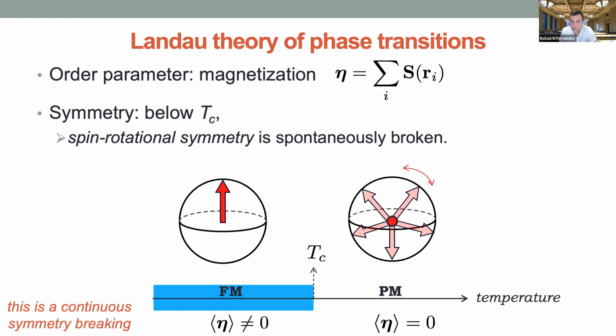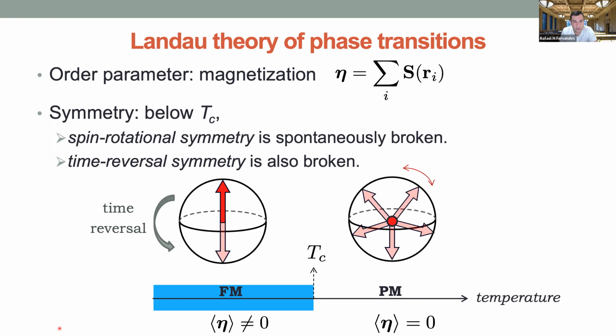So above Tc, the spins can point in any direction, so the system has spin rotational symmetry. Below Tc, spin rotational symmetry is broken. So this is a continuous symmetry that is broken. Time reversal symmetry is also broken, because under time reversal, spin up goes to spin down. And because the spins chose a direction, it also breaks that symmetry.